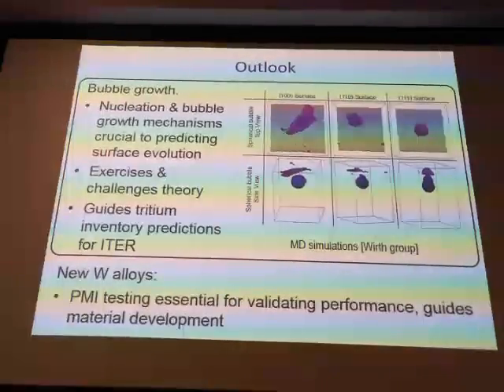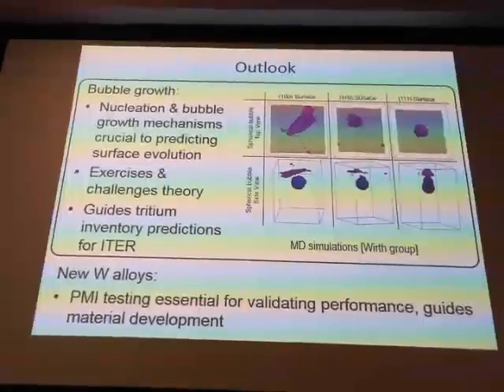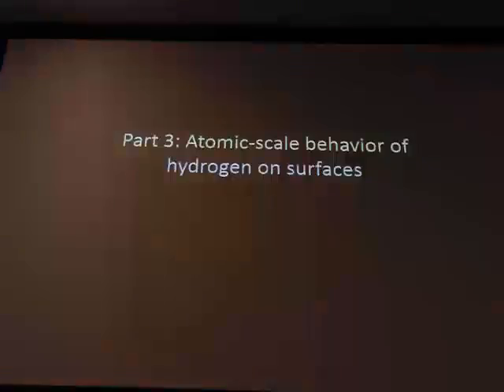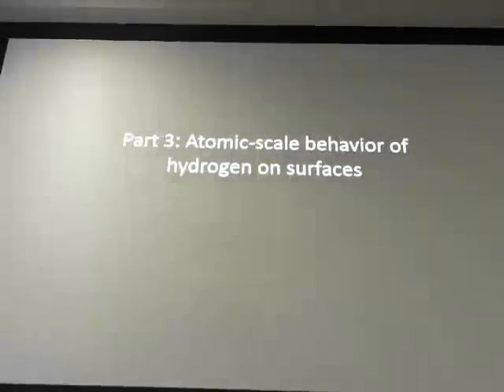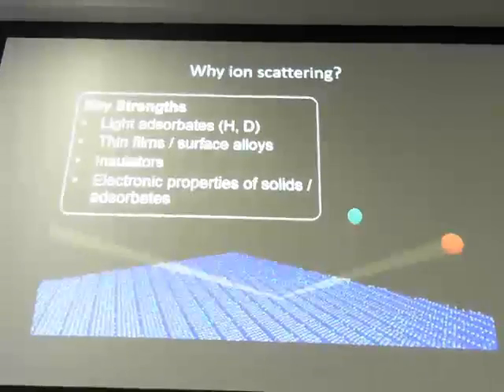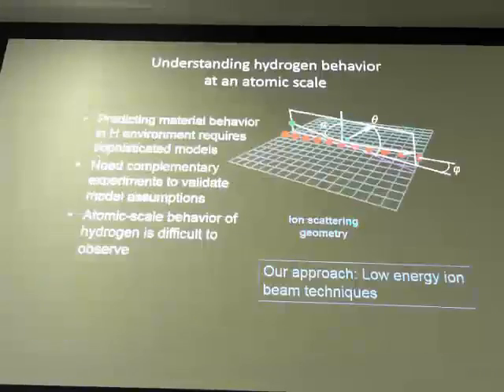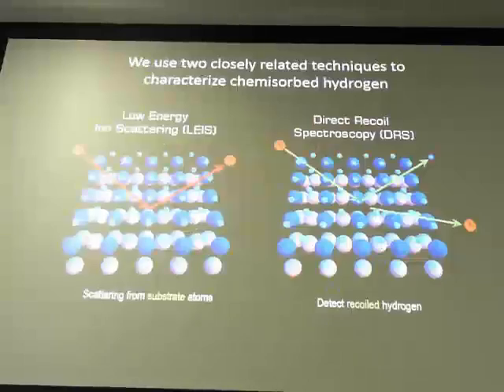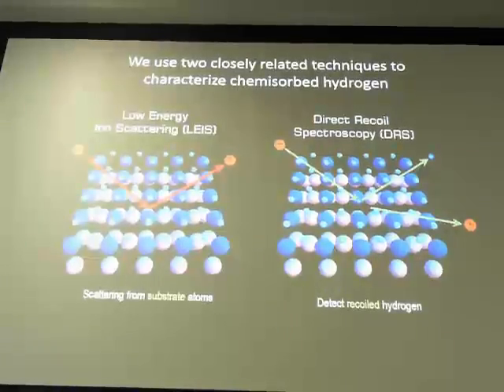Let's see, so I think I'm running low on time, so I'll just very briefly go over the final part of my talk, which is we have a technique for looking at the atomic behavior of hydrogen on surfaces. And we've used a technique known as ion scattering. Ion scattering is a form of low-energy ion beam analysis that, unlike most other surface analysis techniques, provides direct sensitivity to hydrogen and deuterium. These are just introductory slides anyway. The main way in which it works is that you have a beam of low-energy ions that can probe the structure and composition of surfaces.